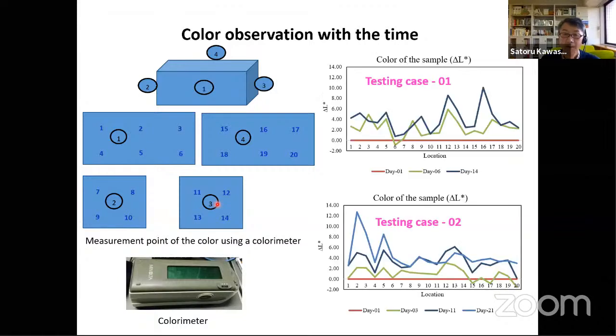This one shows color observation results. We used a colorimeter or spectrometer, like a digital camera. We measured color change at these points. Number 1, this plane, this side, 1, 2, 3, 4. This is the bottom side and side wall. These two indicate the color change. The horizontal axis means the location, the measurement point. And the vertical axis means delta L star. Delta L star is the parameter which indicates black and white. If this value increases, the material's color becomes whitish.